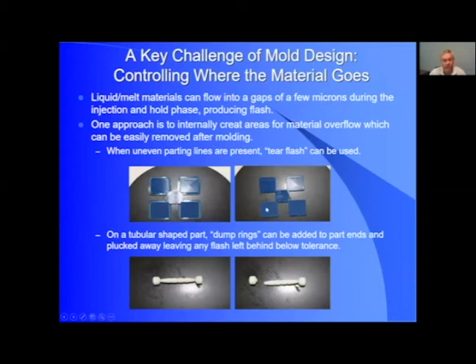Another way you can do it is basically the same thing, only in this case we call it a dump ring. So it's more of a bigger piece. And so you have in your lower left hand corner photograph a cylindrical but tapered component where you might inject it in the center, have the material flow out in both directions. And so you don't have to control it quite so precisely with the total volume. You have these extra pieces at the ends, the little barbells, dumbbell ends that can be basically plucked off at the end to leave your final desired component.